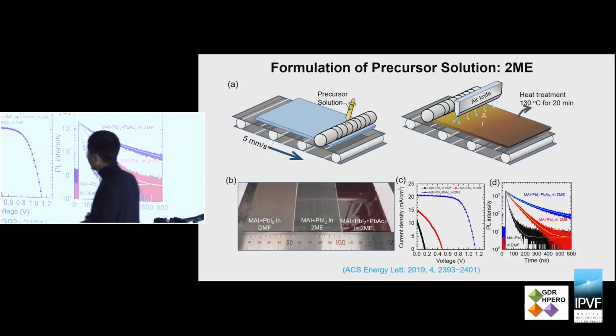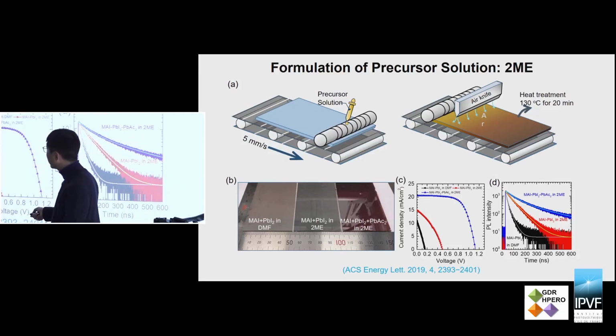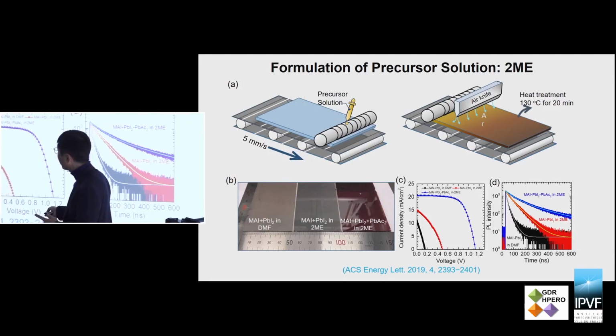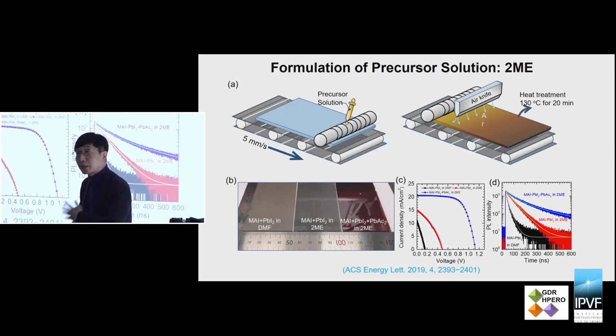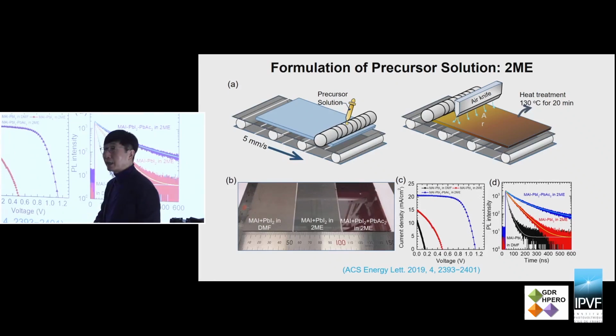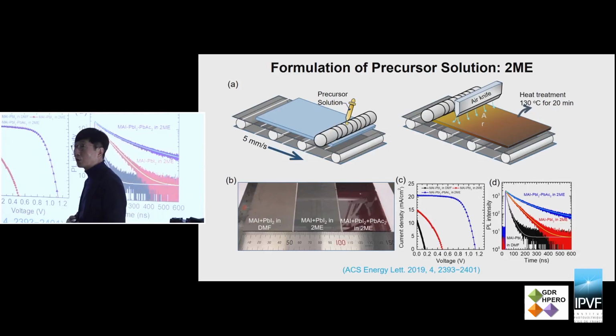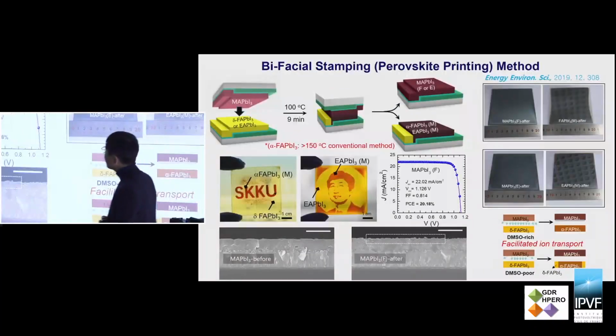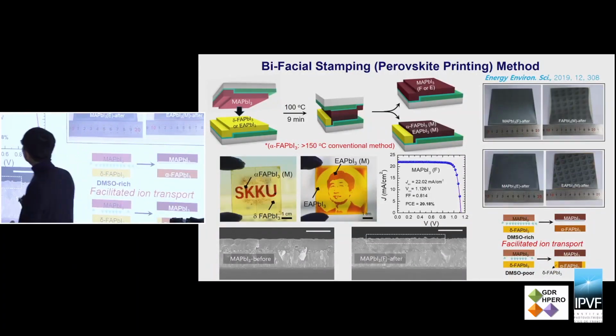formulate a precursor solution, the methyl ammonium lead iodide, the methyl ammonium iodide and lead iodide precursor mixture, dissolved in DMF, which is not good for large area coating because of the high boiling point. Therefore we use 2-methoxyethanol, which has a lower boiling point and easily escapes from the large area. But there is still some problem, so we used some lead acetate to control the interaction between the precursor and the solvent. By doing this kind of formulation technology, we can get the proper efficiency.